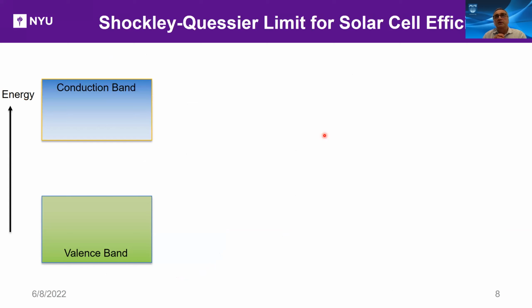The Shockley-Queisser limit for solar cell efficiencies arises from the following fundamental considerations. Typically, you have a semiconductor that absorbs the light and creates electron hole pairs, and that's how one gets the current. If the incoming photon has energy less than the band gap energy of the semiconductor, it does not get absorbed. So you need at least the band gap energy to create an electron hole pair.